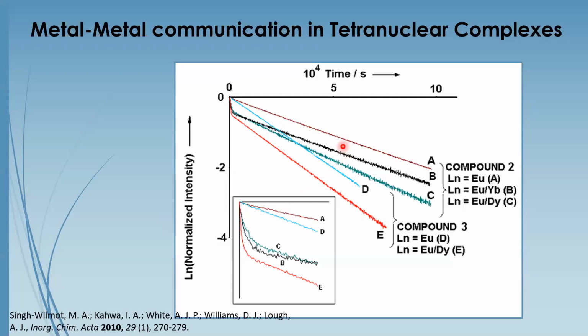If you look, I'll share in a few moments the decay curves, we were able to capture what's going on between lanthanides that are communicating within a cluster. That's in the fast range here. And here on the longer side, the longer decay rates, you were seeing what was happening between lanthanides that were in different clusters communicating via intermolecular interactions.